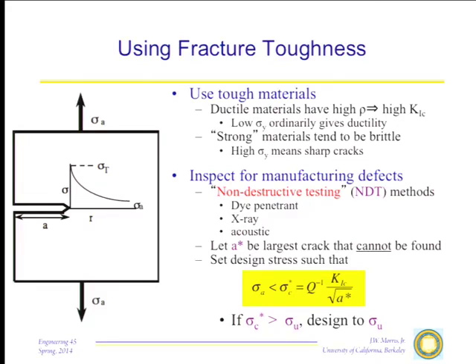You say, look, if the crack's bigger than A star, anybody following the book can find it. But if it's A star or less, maybe it can't be found. You assume that such a crack is present. You give it the worst possible geometry, and you then design your limit load based on the worst crack that can be present, fracture toughness, geometry. You make sure that your applied stress is significantly below that. And if you do that, you're safe.